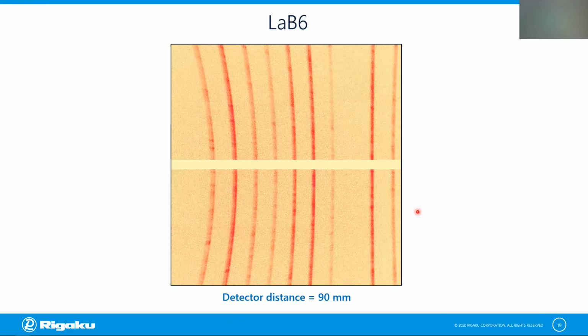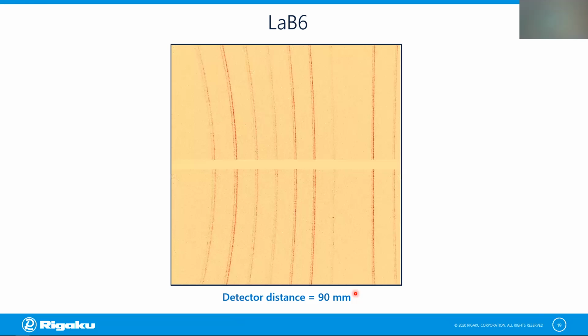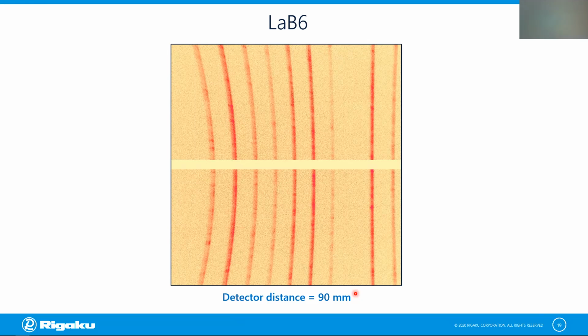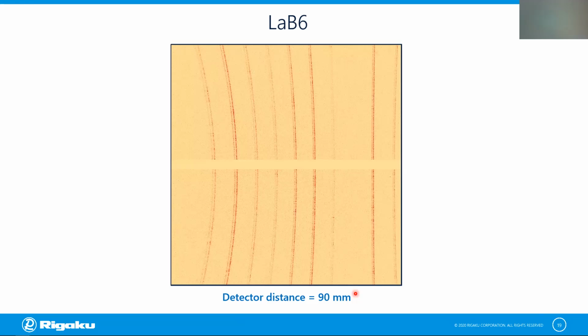In terms of powder diffraction, here is what it can do. This is a diffraction image of lanthanum hexaboride collected with the full beam and the detector at 90 millimeters. When I lowered the divergence of the beam, actually I used the lowest divergence available to me, this is what I got. So these larger rings that I would get with the full beam became split, thinner rings.